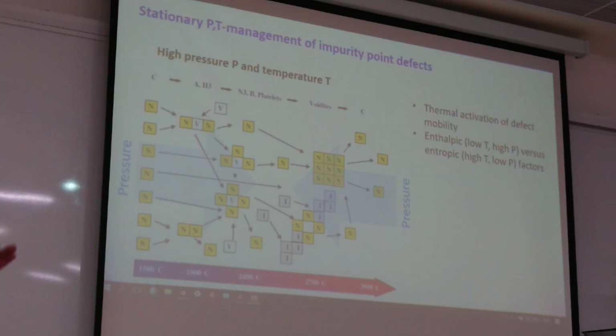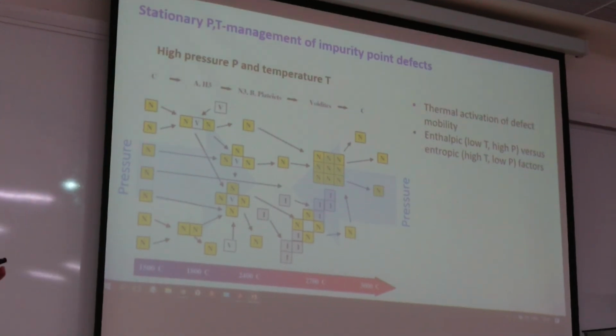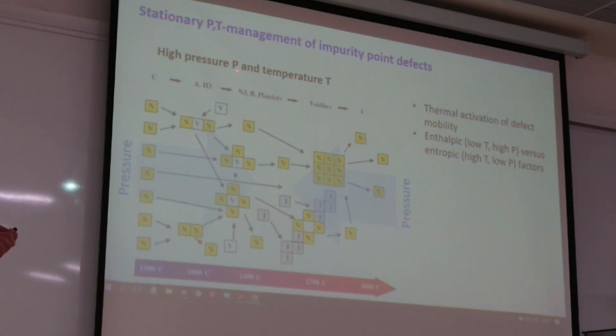There is an opportunity to manage nitrogen defects in diamond using high pressures and temperatures, HPHT. If we start just from very simple atomic impurity defects, just one nitrogen atom occupying the position of carbon in the diamond lattice, and if we increase temperature or increase pressure, we will go to condensation, to increase of size of defects. So defects are proceeding through atomic transformation, combining in two atoms, for example, and two atoms joined by vacancy, and three atoms joined by vacancy, four atoms joined by vacancy, and so on and so on.